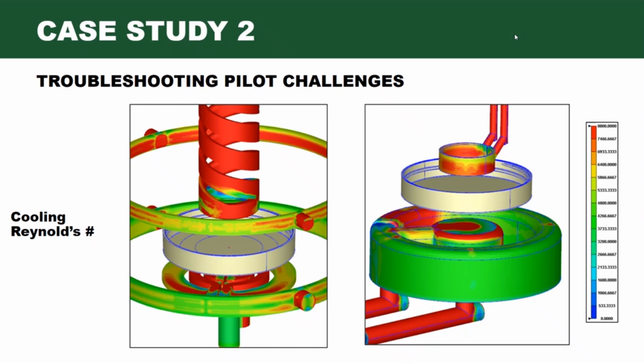So what we did was create new cooling lines, both of them more of a conformal, less traditional approach. You can see on the left, that is a hot drop or a gate insert for a valve gate, and we utilized Mantle's technology to get a conformally cooled gate insert for that. The red shows the Reynolds number, showing the significant spike in turbulent flow, so you're able to keep the steel at a consistent temperature. At the bottom, we did something a little less traditional: we split the bottom cavity in half and put an insert in there so we could place those lines as close as possible to that cap.